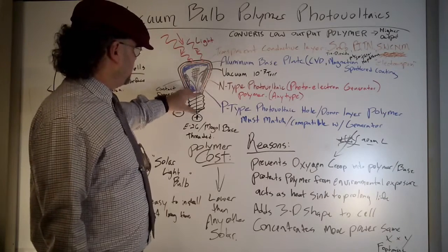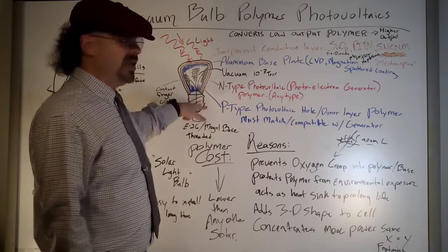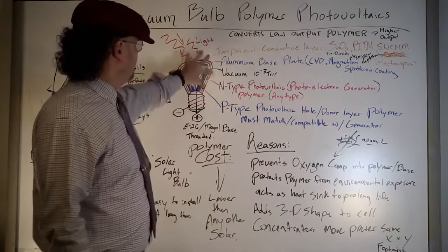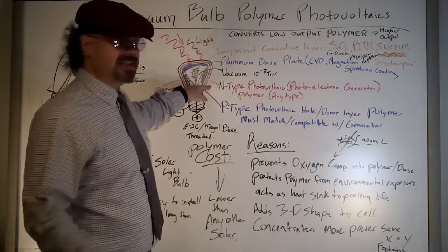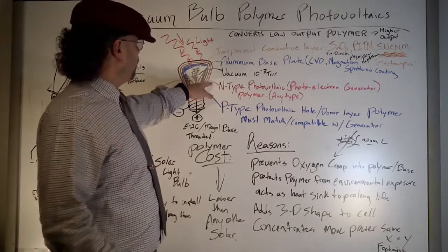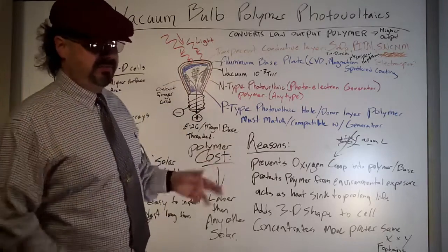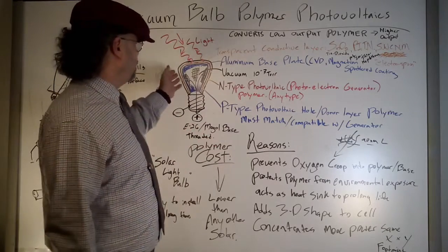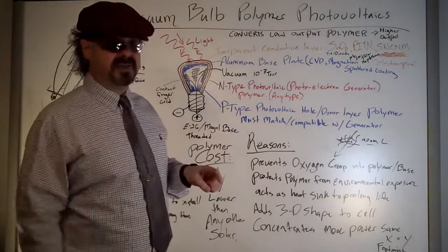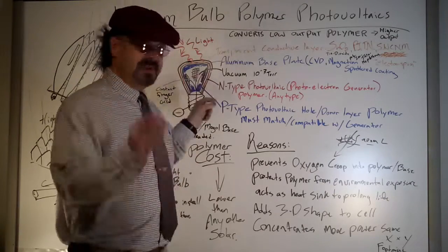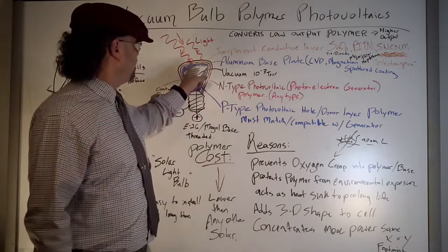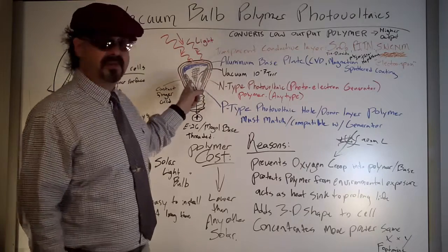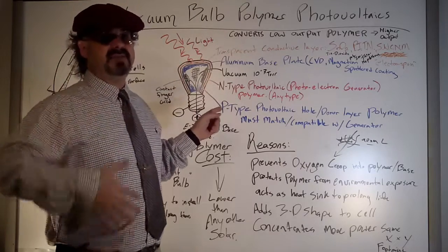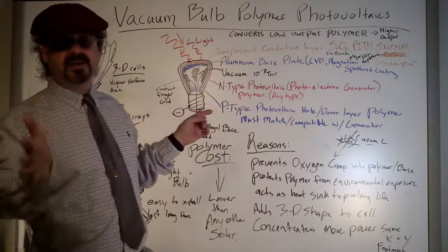This bottom piece right here could be screwed into an actual heat sink so that the heat generated in the glass is carried away. You can make the glass just thick enough, and you can use more thermally conductive glass. You could use fused silica, or quartz. You can use a lot of different things that have a higher thermal conductivity, but I think glass will be enough. You can make the thickness just thick enough so that it carries the heat away from the polymer surface at a rate high enough to maintain the integrity of the PN junction and the polymer itself.